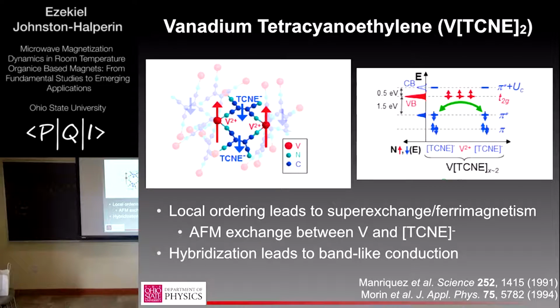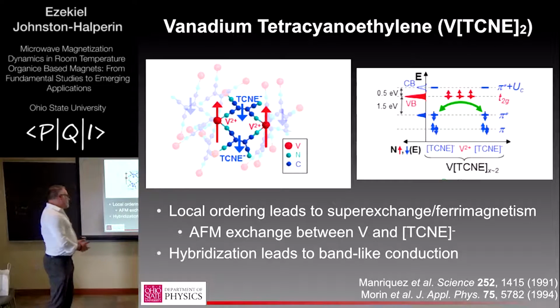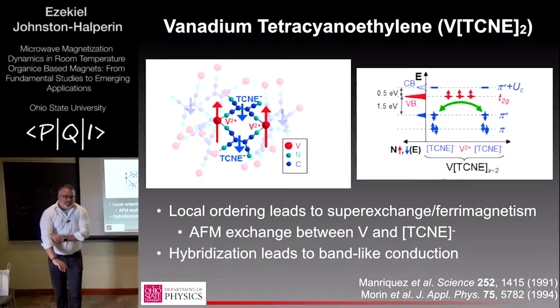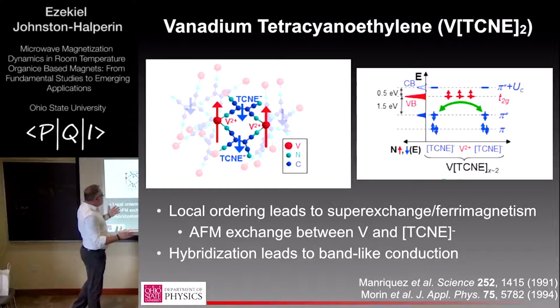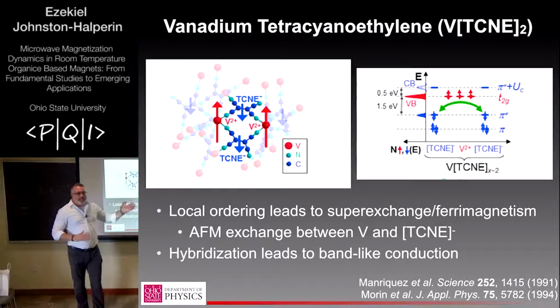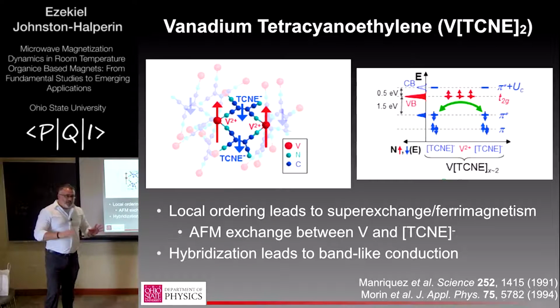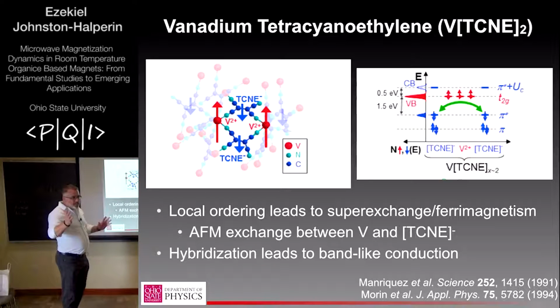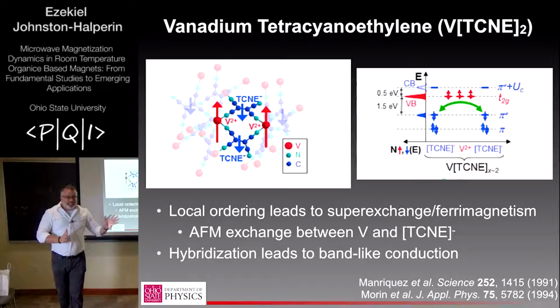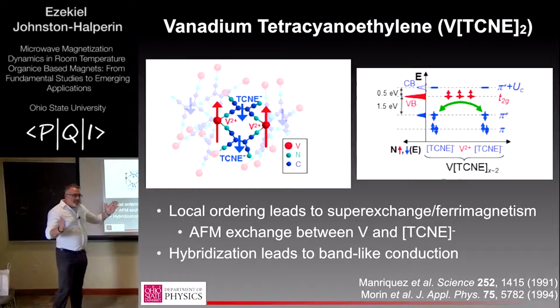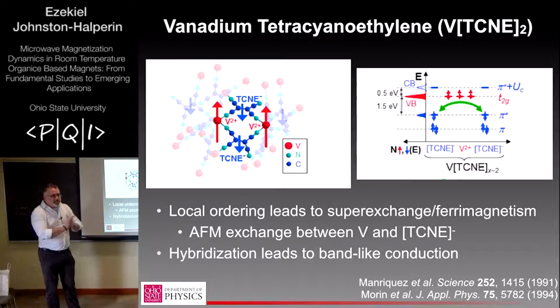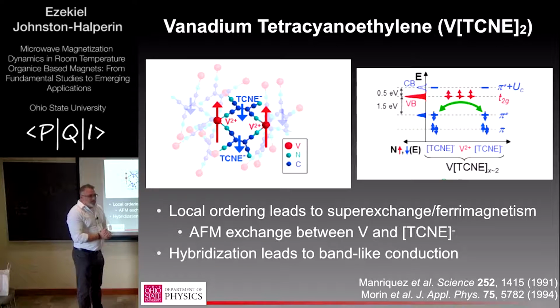So you can do thermal activation measurements and you get an activation energy of half an eV. If you believe a simple band model, then that's where this comes from. But if it's a hopping conductor, then that activation energy means something different. Conventionally, the solid-state physics way to resolve this is to do a careful temperature dependence and do log-log plots. The challenge here is that this material is deposited at about 350 Kelvin. That's where it grows, so you can't make it much hotter than that without decomposing it. And if you cool it down, the carriers freeze out by about 150 Kelvin. So that's just not many decades of temperature to get a reliable fit to do these power law analyses and say, well, this really is hopping, this really is band-like, this really is whatever.